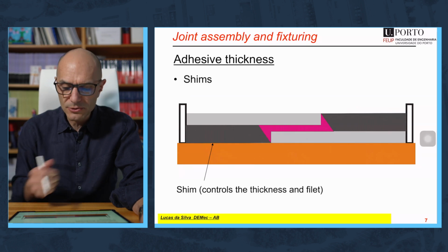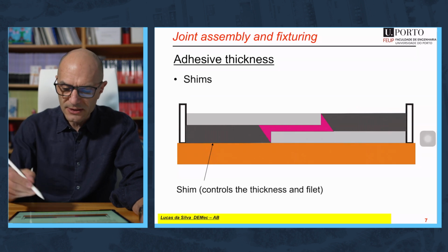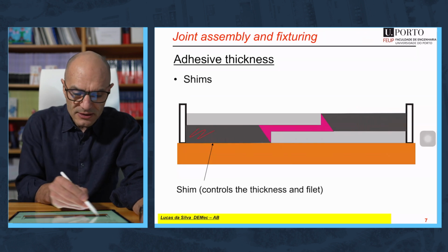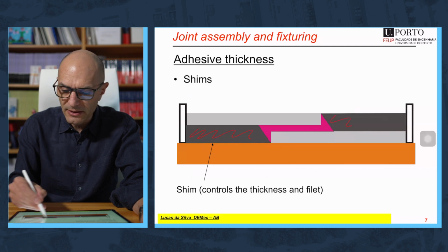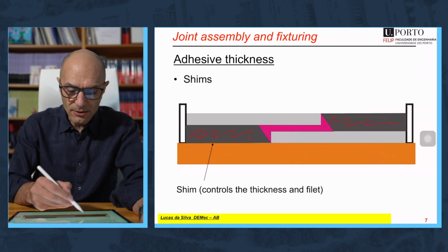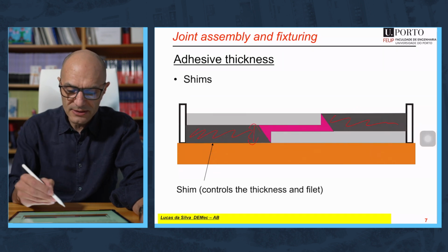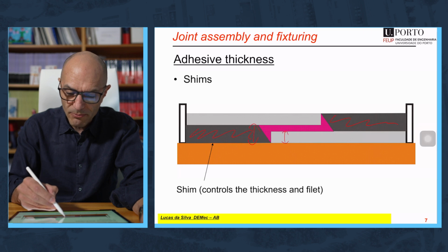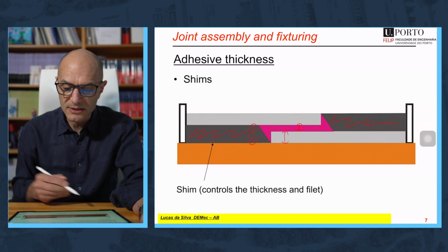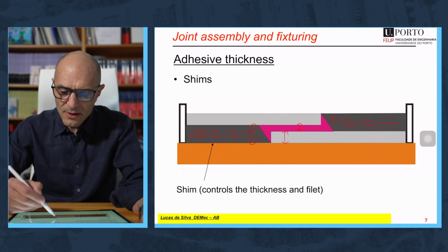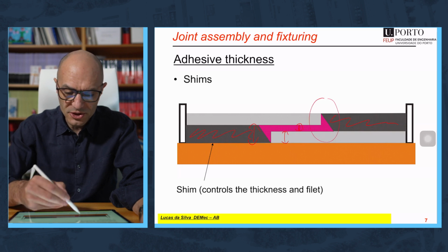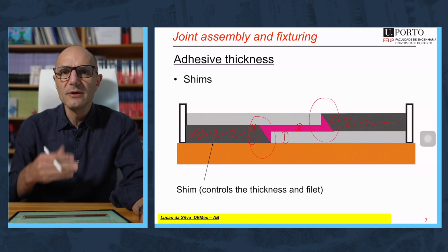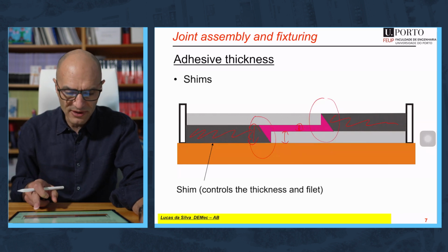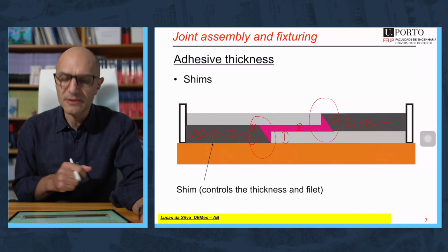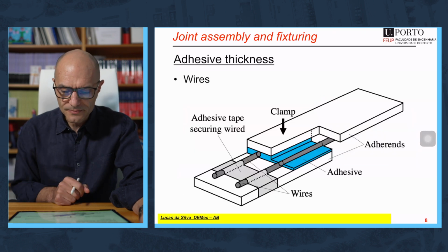Shims also can be used, such as indicated in this scheme. So you have the joint here, and this part here, this is a shim, and this part is the other shim. And the thickness of the shim is equal to the thickness of the substrate plus the thickness of the adhesive. You can even use shims with a shape that can give you the final shape of the spew fillet. This also has an effect in the final joint strength.